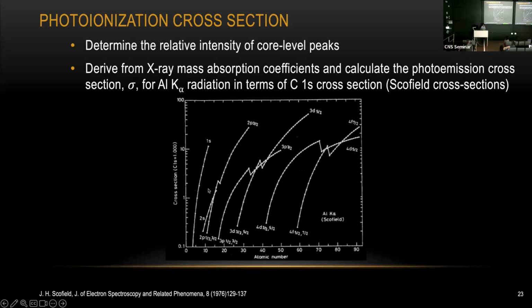So for instance, if you're working on silver with atomic number 47, look for 47 here and go up. You can see the most probable peak you're going to see if you're working on a piece of silver will be the 3d 5/2 peak. But if you're working on carbon with atomic number 6, you go up here, and you can see the most probable peak will be the 1s peak. So that gives you an idea which element and which signal you're going to see most of the time.